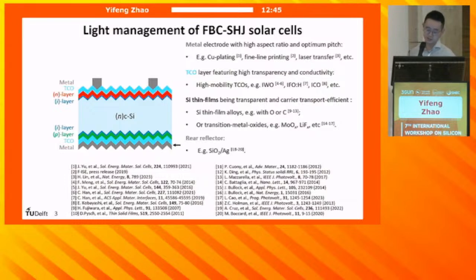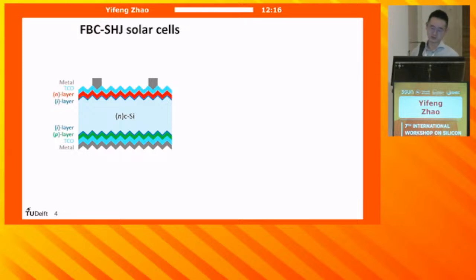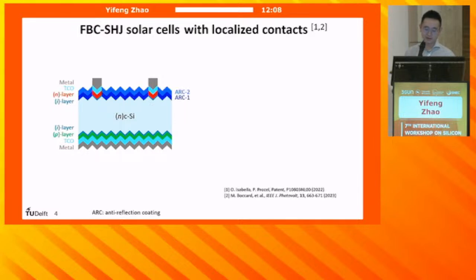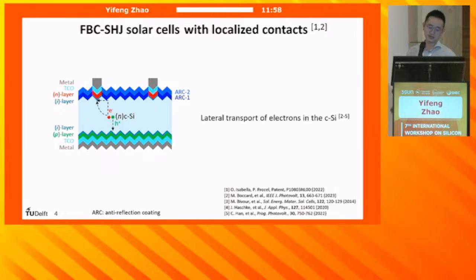Last but not least, you can also enhance the infrared response of the heterojunction solar cells by adding a rear reflector. So overall, improving the light management of front-back contacted silicon heterojunction solar cells, especially minimizing the parasitic absorption losses in the TCO layer and silicon thin film layers, often involves a trade-off between the optical and electrical properties of the layer. So what if, instead of considering all these trade-offs, we simply localize those TCO layers and the silicon thin film underneath the metal contacts? Then we can deposit anti-reflecting coating layers on top, and we form the so-called front-back contacted silicon heterojunction solar cells with localized contacts. In this design, the collection of electrons relies on their lateral transport in the crystalline silicon bulk.